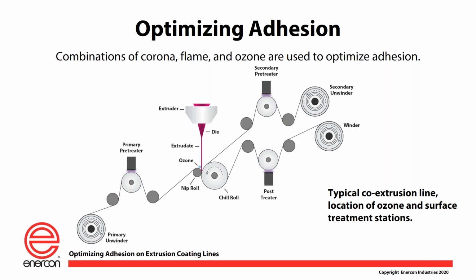Now, if we take a step forward, follow with me to the right on this slide. Let's say we have another unwind here, and this other unwind has the ability to introduce yet another secondary web into the process. So we're going to go from an extrusion coated product to an extrusion laminated product. That secondary unwind comes off and goes through yet another surface treater. Let's say, as an example, we're going to unwind some foil. We're going to treat that Class A foil so that we thoroughly clean it and get any remaining oils off that foil before it gets down into the nip area, where we extrusion coat the other side.